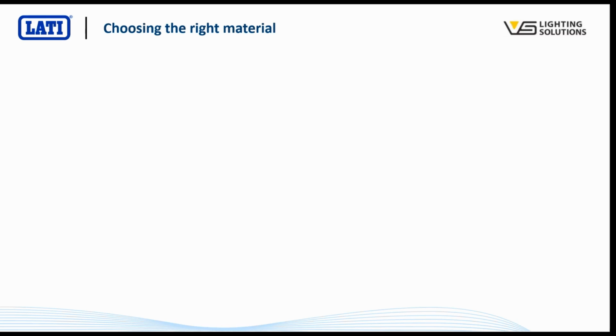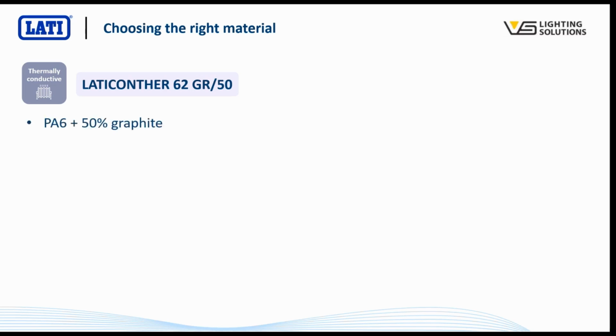So again, as we did last time, let's start by looking at what sort of material we might use. And I think fairly obviously here we're looking at something from within LATI's thermally conductive material range. In this case, the grade that we looked at is a grade we call LATICONTHER 62 GR/50. So this is a nylon 6 material with 50% graphite in there as the thermally conductive additive. So this is a grade with outstanding thermal conductivity. In fact, it's one of LATI's most thermally conductive grades.